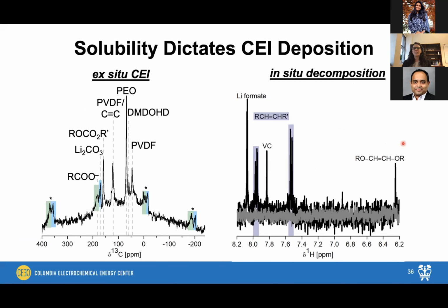So what we did in order to actually figure out what was happening at the surface of these composites in terms of the organic decomposition was an in situ proton NMR experiment. So here are the results from the in situ proton NMR. And what I'm showing here is that as soon as we start cycling to high potentials, we see the formation of a wide range of vinyl decomposition products. We also see the formation of this DMDOHD, which is just a carbonate breakdown product. So these vinyl products are likely contributing to this resonance here at about 120 ppm.